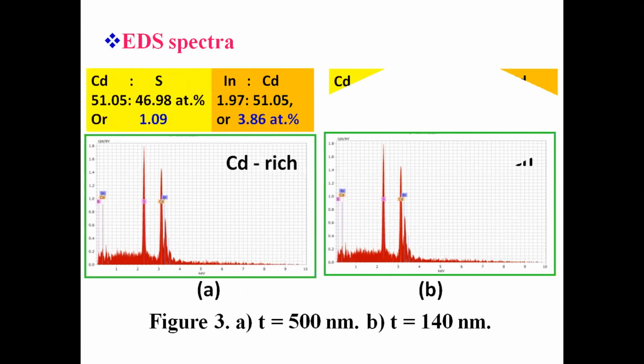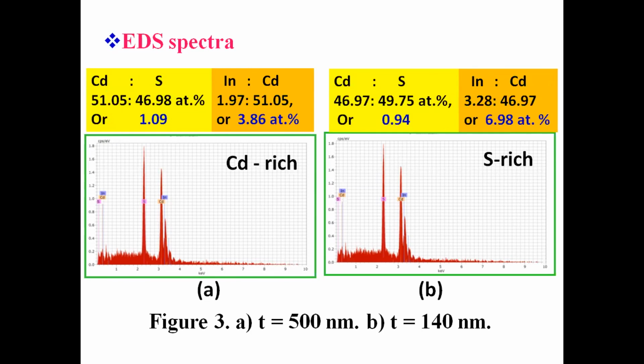Okay. As far as I recognize from here, you have indium as well, and also S, but cadmium is a little bit in here. And which branch does it come from? These are only cadmium and S, right? And indium and cadmium proportions. But I mean that there will be oxidation also and other kinds of elements, for example, carbon. But the instrument didn't find them. Just these were found in the samples. If there are such elements, they are traces and cannot be detected by the instrument. Only K branch comes from here, right? Only K ones, not M shells, I mean the electron shells. Just we found cadmium, sulfur, and indium. No other elements.